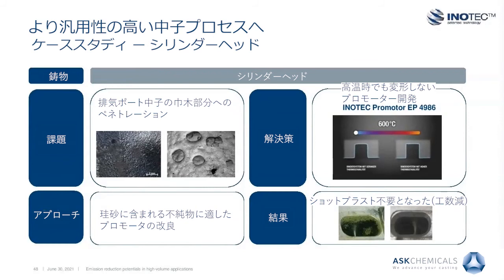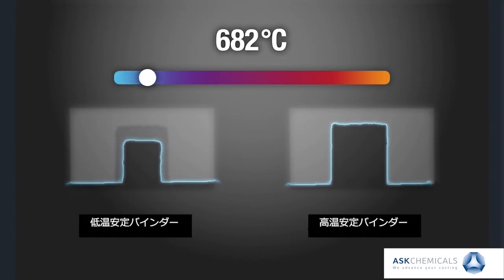In this case, ASK is able to fine-tune the performance properties of the INOTEC promoter to the local sand quality used. As the components of both silica sand and the promoter are of inorganic nature, an interaction is commonly observable and changes the properties of the sand core, for example the thermal stability. Thermal stability describes the resistance of a sand core towards thermal and mechanical strain of the casting process, and it is an intrinsic property of the binder system itself, characterized by the so-called softening temperature. The softening temperature of a binder system can be monitored using heating microscope technology.